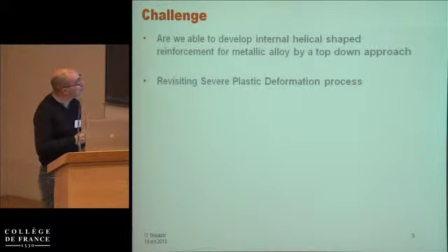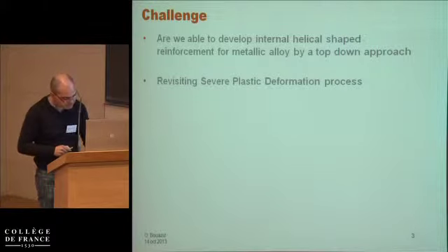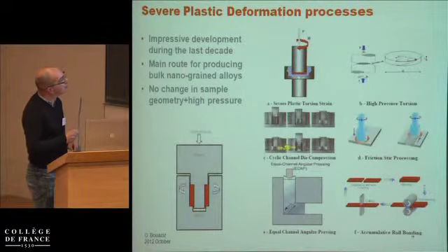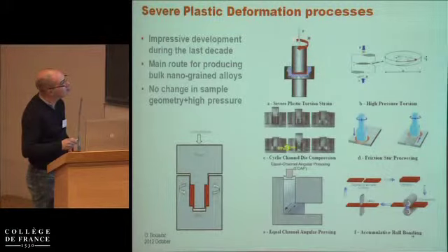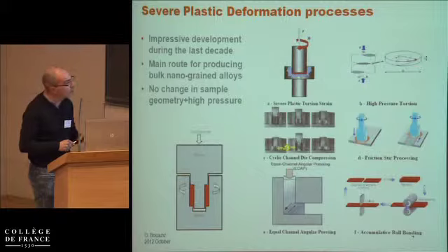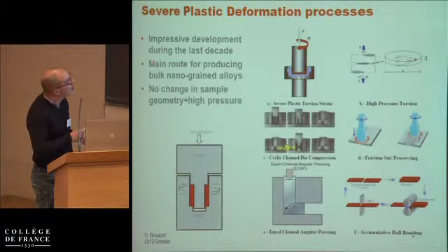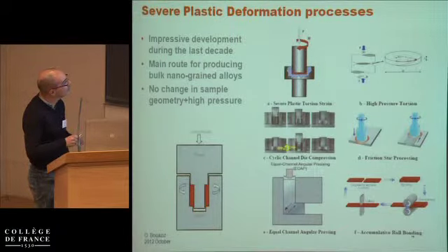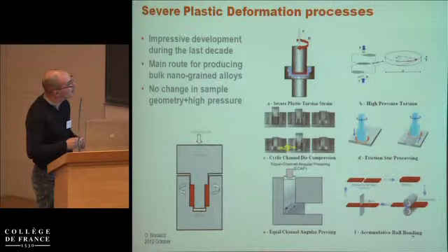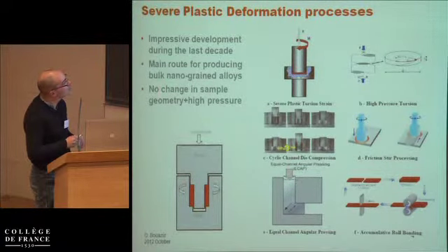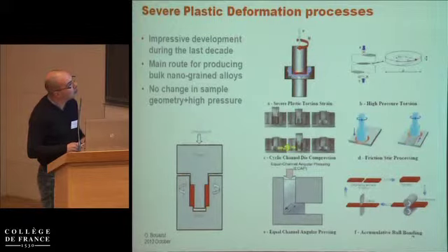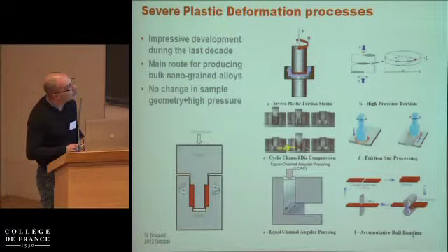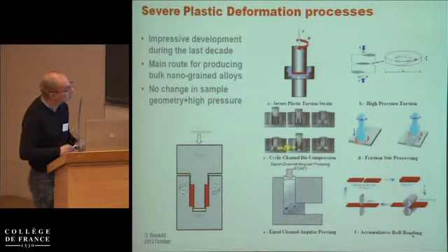To do that, we are going to revisit the severe plastic deformation process. Severe plastic deformation is a process to deform a material as much as possible, more than 1000% for instance. The development around this technique has been impressive during the last decade, and this is now the main route for producing bulk nanograin alloys. The principle is no change in sample geometry, plus a high pressure, like in high pressure torsion, where you have a disc, impose the pressure by axial load, and twist as much as possible to a cumulative plastic strain.